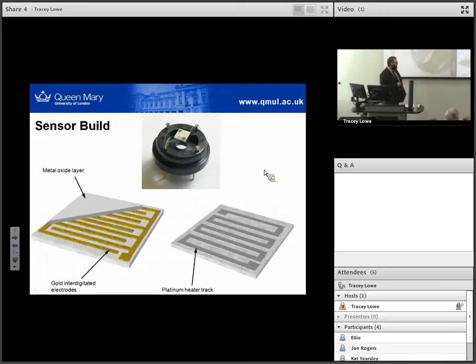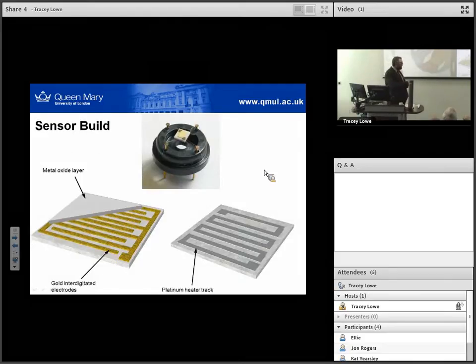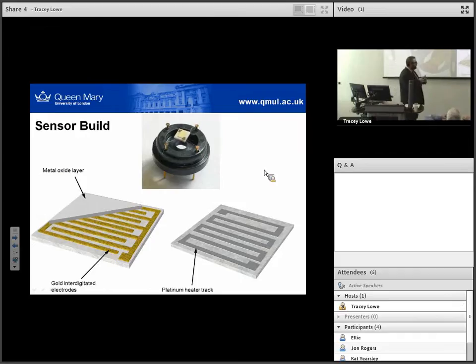So, sensor build, what are we talking about? Our sensors are based on this gold interdigitated electrode. Metal oxide layer goes over the top. On the back of our chip there's a heater track which we apply current across - resistive heating, continuous current, you get continuous temperature. The finished device looks something like that. This alumina chip's area is about 2 square millimetres, so they're quite small, very tiny.